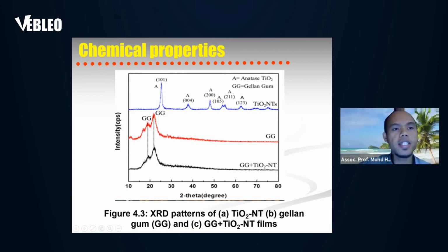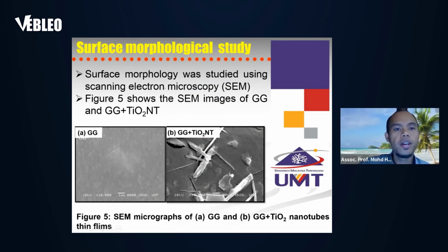Right. So next we see the surface morphology of both films using scanning electron microscope, SEM, and then we can observe very nice surface morphology for the pure GG film. Okay, very smooth surface. And then for the GG plus titanium dioxide nanotube film, we can see the presence of elongated structures. Okay, some kind of rod shapes. That means the nanotubes are present on the film. So that's why we can observe the large nanorod shapes of nanotubes in this film. Right, again, this just confirms the presence of titanium dioxide nanotubes on the film.